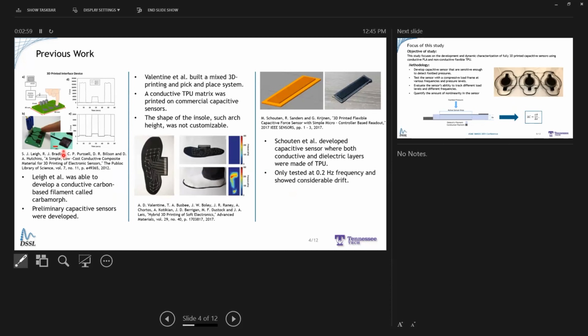Some previous work in this area: first, Leigh et al. developed a conductive carbon-based filament for pressure sensing applications and applied it to finger pressures. Valentine et al. took a similar but slightly different approach by printing a flexible TPU matrix on an insole and then using a pick and place machine to place commercial capacitive sensors into this matrix to sense pressures. While this could customize for size, it couldn't customize the shape of the insole. And Schouten et al. was able to 3D print a fully TPU capacitive sensor, but these sensors were only tested at lower frequencies of 0.2 hertz and showed considerable amounts of drift.